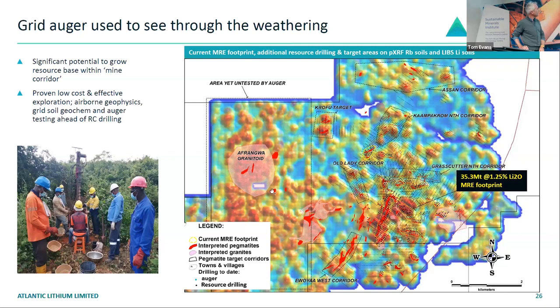But you can see here, the image below is a combination of rubidium and lithium in soils. And then in red are the mapped pegmatites to date, the current resource footprint predominantly in this area. And then the larger black dots are our resource drilling. So we've drilled 150,000 meters to date in roughly 800 holes. And then these finer dots here are all individual auger holes. So you can see we highlight an area of coincident geochem and geophysics and then go into that area and map. And if we identify outcropping spodumene, it really prioritizes that target. Otherwise, it's just a grid auger drilling pattern. So this is like a corridor of anomalous results, as is this area here and this anomaly here, which is the Krofu target, which has lithium mineralization.